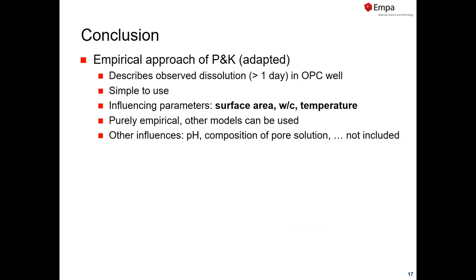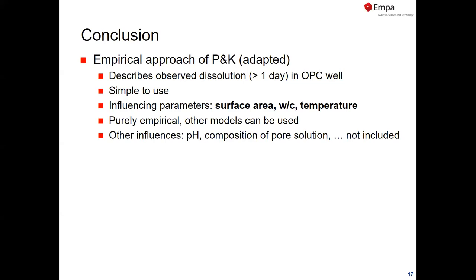So before we start our modeling, I want to emphasize again that the empirical approach of Parrot and Killoh works nicely for most Portland cements. It describes the observed dissolution particularly at times longer than one day, it's simple to use, we only need a few parameters, and it's purely empirical. Any other model you can use is up to you. You also have to be aware that influences of the pore solution — like pH, alkali presence, and sulfate presence — are not included, mainly because at the moment we do not understand those factors sufficiently.